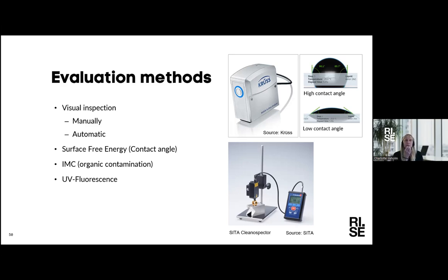The method is that you heat up the surface and then detect. You can detect all organic contamination or compounds on the surface, but that's not an inline method to use. If you want to check a batch, then that can be used. There are also methods that use UV fluorescence, as the SITA Cleanospector to the right is an example of, but there might be more methods, of course, and it also has to be tailor-made for the system used. And some of them have their limitations.